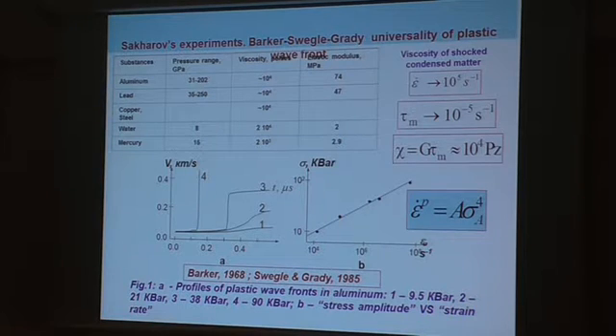I would like to attract your attention that this kind of similarity that is close to Paris law in terms of the delta K for high cyclic fatigue reflects very strong power of collective behavior of defects at the crack tip area, because similar structure we have, for instance, if we have shock wave loading of materials, metals, for different intensity, and estimation of the slope of this plastic branch every time gives 4 power or close to here. It means that collective behavior of defects at the crack tip area, due to the very high coherent behavior, could provide some similar properties that could subject crack dynamics like in the Paris law. It's my conclusion.